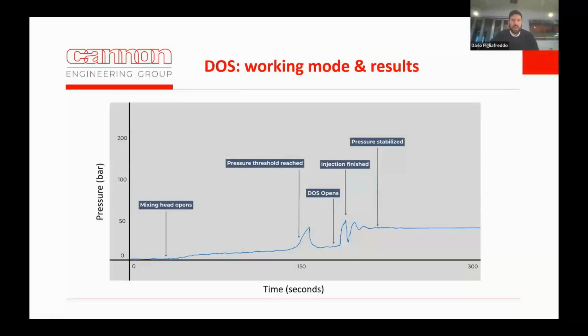Now, to better understand what happens during an actual injection, I'm showing here an example of a pressure profile in a real component. At the beginning, you will have the start of injection, opening the mixing head, and a slight increase in pressure because, again, as Shane said, the reinforcement is resisting the flow of material. At a certain point, you will have a peak of pressure because there will be no space left for the material to go. In a normal HPRTM process, you would close the mixing head, but in the DOS application mode, you open the DOS, the pressure will decrease, and you keep injecting.